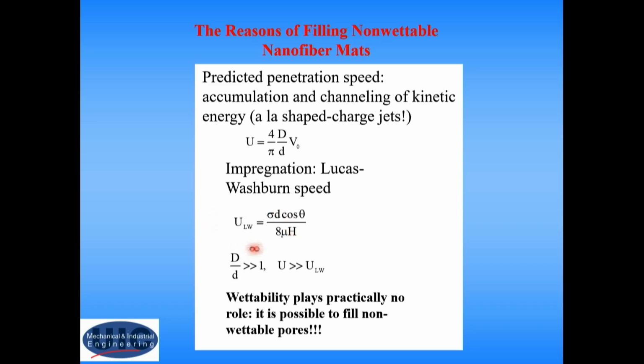So after all, the Lucas-Washburn speed is very, very small compared to this velocity u you predict here. So it means that when you have a drop impact on a droplet which is much larger than the pore size, what happens here is a phenomenon we called hydrodynamic focusing. This is a phenomenon where you bring kinetic energy and suddenly let it go only through a very small outlet. And this kinetic energy, even though not huge originally, when you focus it into tiny droplets or a tiny pore or several tiny pores, becomes a tremendous speed.